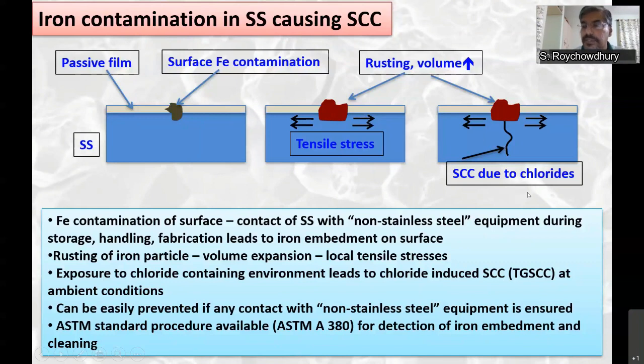And during long-term storage or during operation, or when this part gets exposed to, suppose, a marine environment, even at room temperature, in the presence of chlorides, it will undergo TGSCC, and the SCC crack will grow. So there are various standard methods. ASTM standard method like A380 gives a procedure for detecting such iron contamination, along with its cleaning procedure.